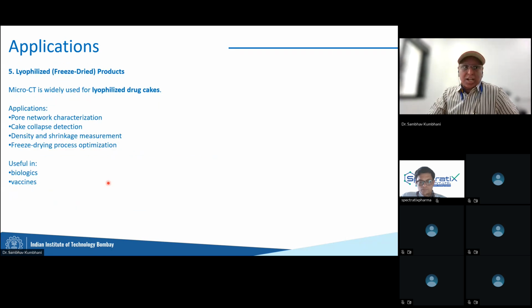Lyophilization. So when you freeze dry something, nowadays freeze drying is very common. We have foods that are freeze dried all the time. We just add hot water and you get your ready-to-eat food, right? So that's essentially the principle used by pharma also in many cases to remove the water content out of the formulation. After the water is removed, it really damages the structure of your physical form. I mean, when I say structure, I mean the physical form of the API or excipient or whatever formulation it is. So again, CT can help you see the difference of what happened before and after freeze drying.